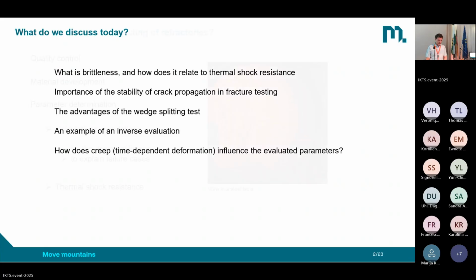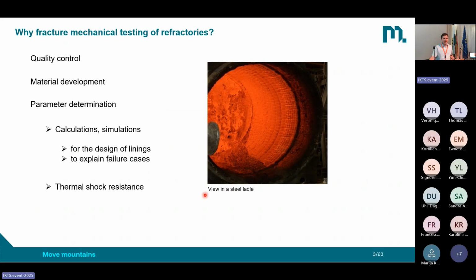So why do we need fracture mechanical testing of refractories? First of all, we have the quality control. So you have to do it according to the standards after the production process to know which strengths your materials have. Then you need it for material development, for sure. You would like to know which strengths your material have, you develop. And then there is one section I call parameter determination, with the goal to have input parameters for your calculations. So if you would like to have an idea about the thermal shock resistance, if you would like to have an idea about the stresses you will have in the application in the refractory material, and if you like to have the parameters for a finite element simulation, then you need these parameters.